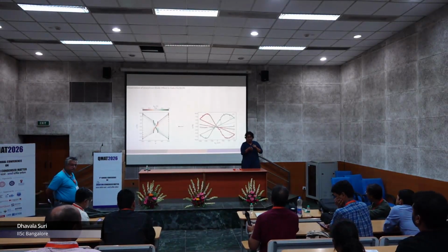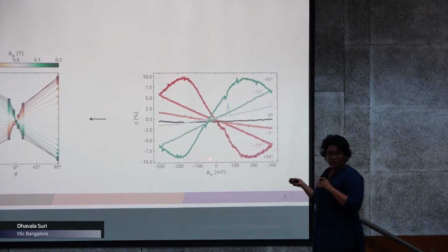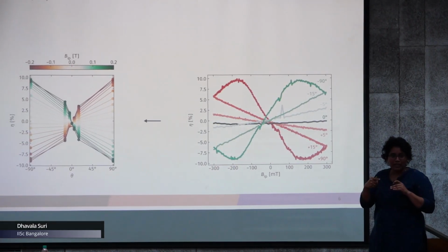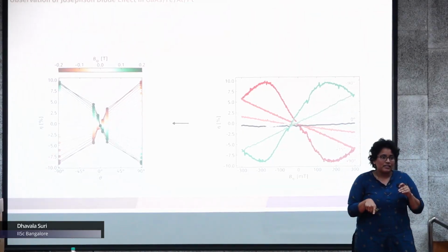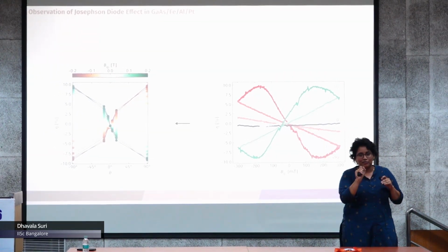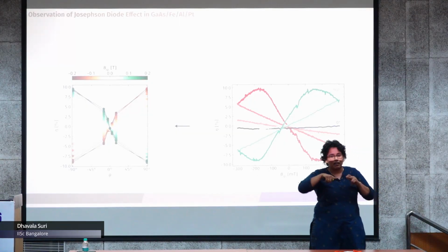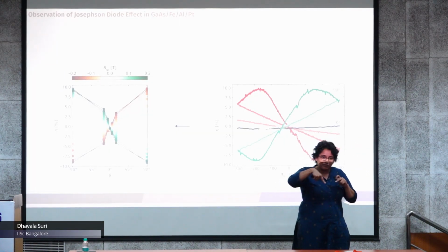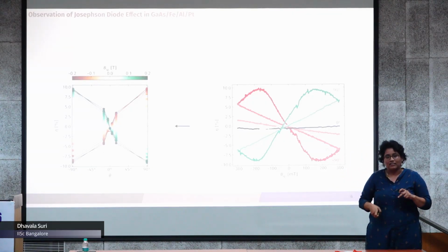Right. It's actually a very good question. In fact, a lot of careful experimentation is required to eliminate or rule out the role of vortices in this. But here, in this curve, this is a magnetic field applied in the plane, so there is no role of vortices. What you're saying is right in the sense that even a one Oersted field is enough to cause this, so a careful alignment is necessary. The way we did this was to have a strip of aluminum whose critical field is low and then align with respect to that. Okay.